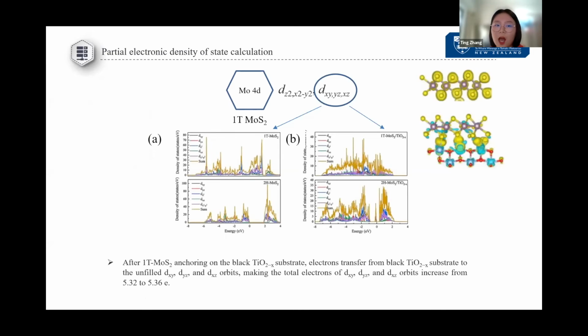To further analyze how the electrons transferred in the 1T-MoS2 before and after the decoration of black titanium dioxide, we did the PDOS calculation. As we explained before, there are only 2 electrons distributed in the Mo 4d orbitals dxy, dyz, and dxz. And we said if we increase the electrons in these 3 orbitals, then the stability of 1T-MoS2 can be enhanced.